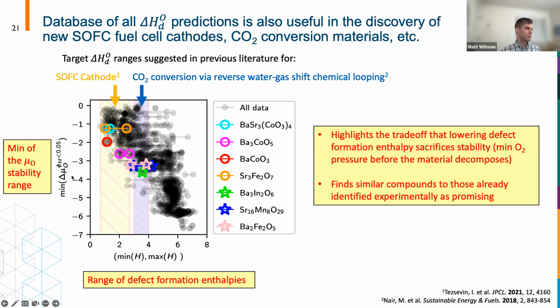Here I'm showing the minimum stability of the material at the oxygen chemical potential versus the range of its defects. So again, you see this classic defect trade-off where the lower and lower the defect formation enthalpy gets, the less and less stable your material is at higher reducing conditions. So that's the trade-off that we're going to constantly be operating in across all these applications. So we want to pick out materials that are on the lower bound of this Pareto front. When we do this, we actually find materials that people have considered experimentally for these different applications, and we can suggest new ones.